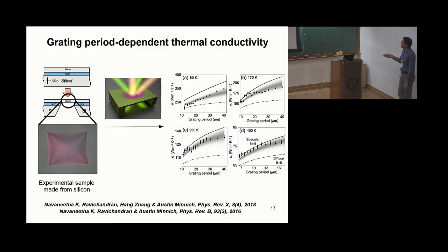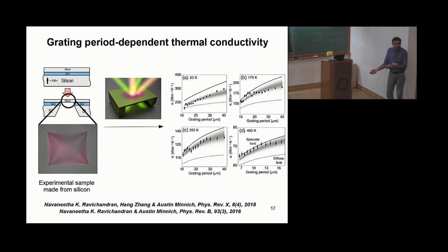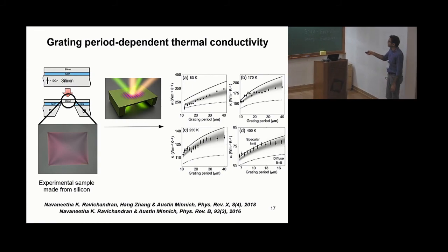For example, here I'm showing a few plots at different temperatures for thermal conductivity of silicon, and you can see that the thermal conductivity is decreasing as the grating period is decreased. These dots with error bars are the measured thermal conductivities at 80 Kelvin and so on.